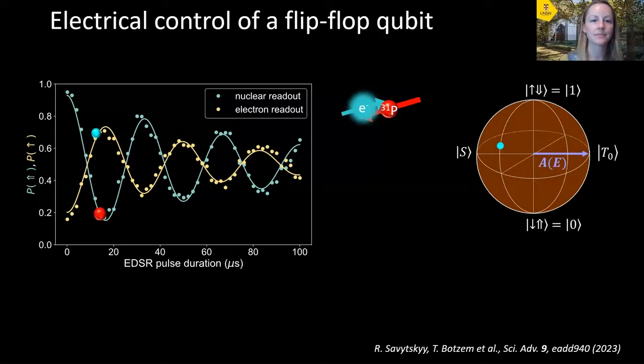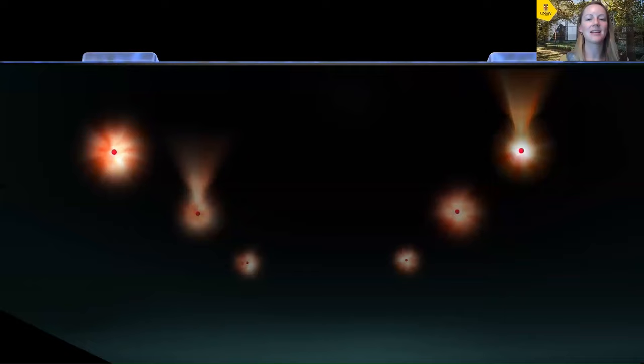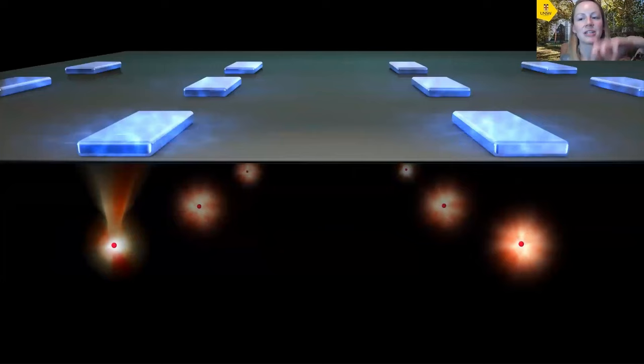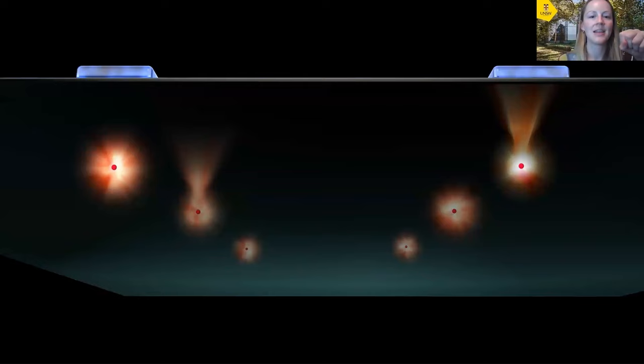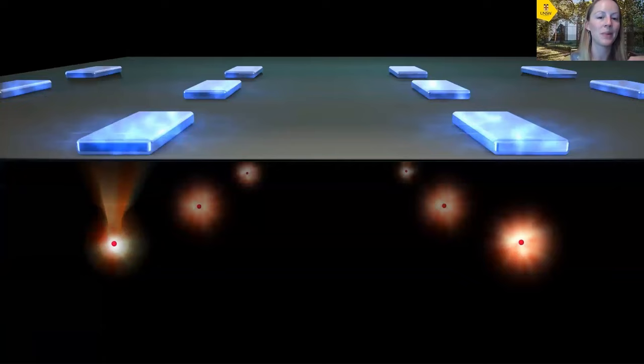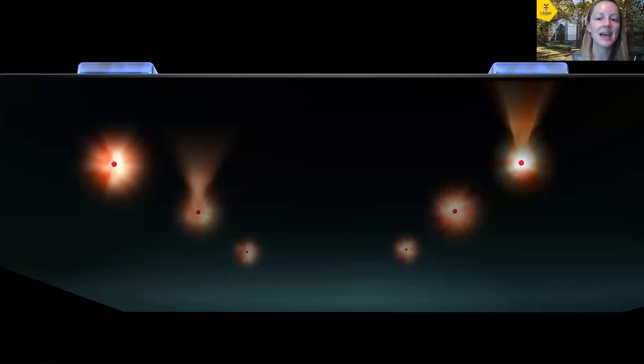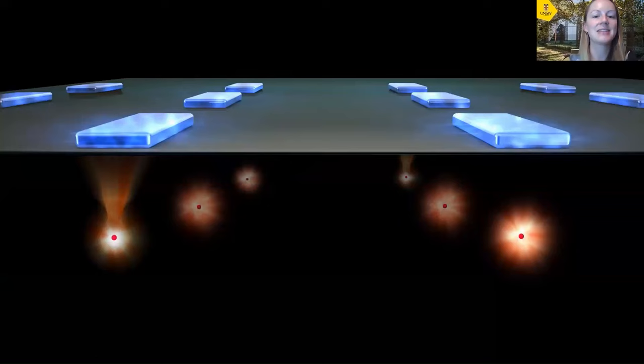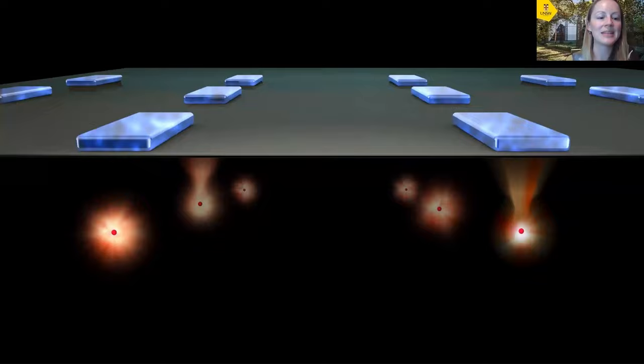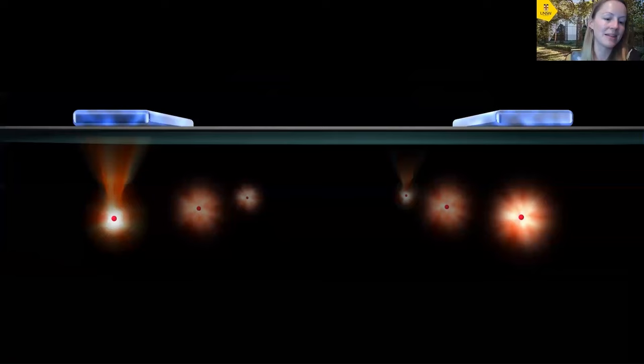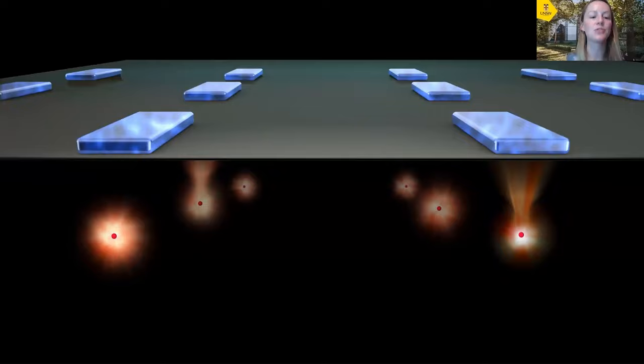So with the flip-flop qubit, the nice thing is that we can use the fact that when the donor electron is ripped away from the nucleus, it creates an electric dipole due to the charge separation of the electron from the positive nucleus. And this allows flip-flop qubits to interact with each other using the dipole-dipole coupling, which is a long-range interaction, which makes it insensitive to the exact placement position of our donor qubits, which makes it the perfect architecture for our ion-implanted donor qubits, because with ion implantation, you will always get some uncertainty in the final resting position of your donor when it's implanted in the silicon. So this is a very nice flip-flop qubit architecture that's suitable for our method of fabrication.